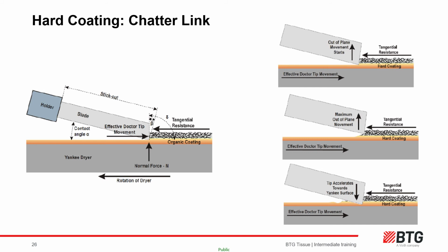However, then we go to the top right, and the cured coating layer, or the coating itself due to the release being too low for example, has started to become hard and or dominant over the soft robust coating. The hard coating and resistance from it to the doctor pushes the blade out of plane and momentarily away from the Yankee. The blade skips out, but loading and mechanical forces prevent any further out of plane movement, and the blade then accelerates downwards into the coating layer once more, hopefully stopping before it penetrates through to the Yankee surface. This happens so quickly that it repeats and resonates in millisecond intervals, and you end up with a band of chatter. How CD uniform the coating rheology is would dictate the CD extent of the chatter.